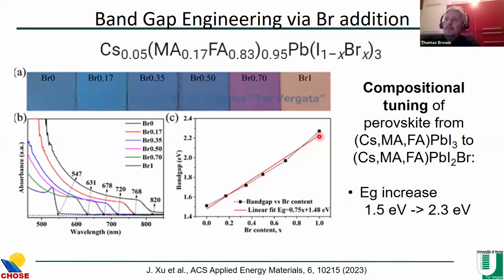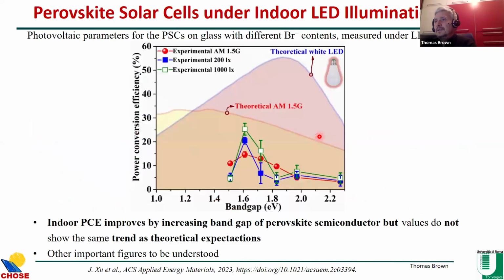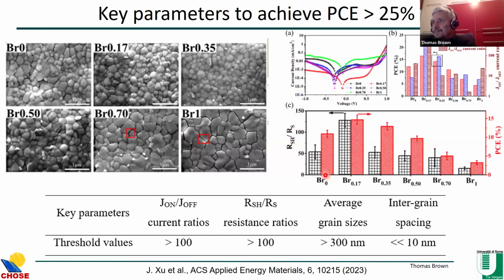So we developed these films and constructed perovskite solar cells, hoping we get the best efficiency at 1.9. But actually, we do get an improvement in efficiency going from 0 to 17% bromide. So the band gap goes from 1.5 to 1.66. But after that, the efficiency goes down. So we needed to understand why.